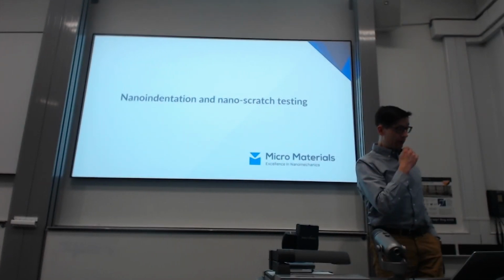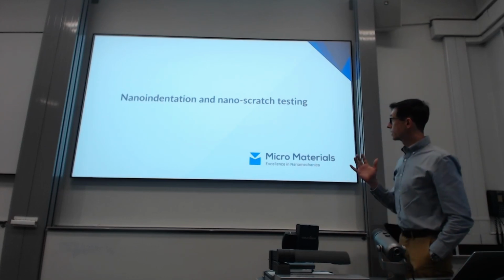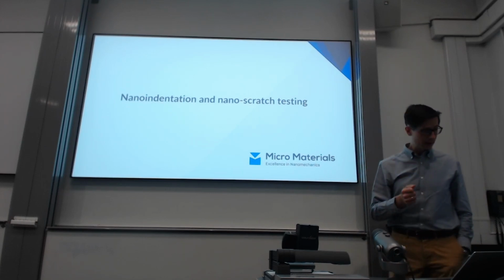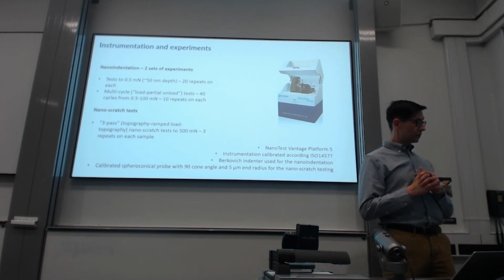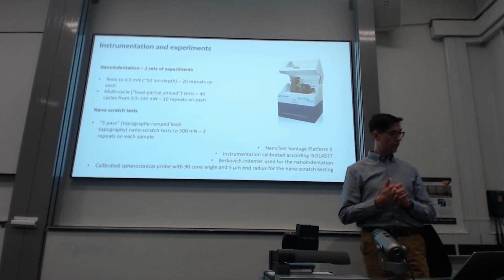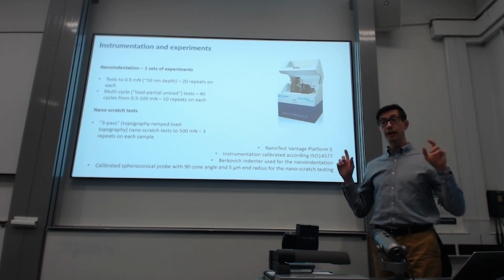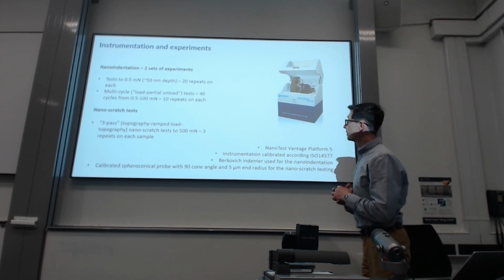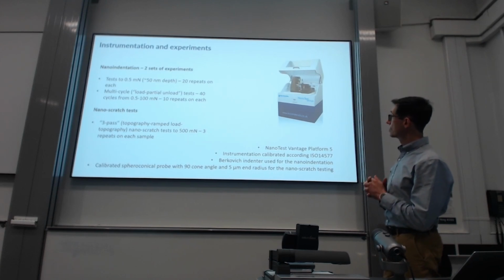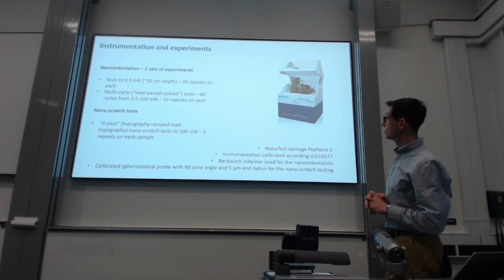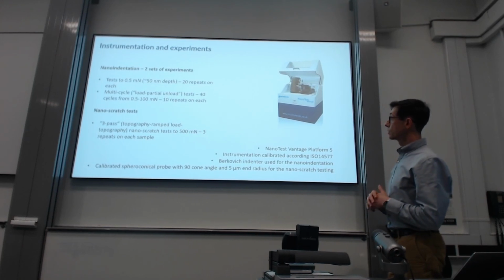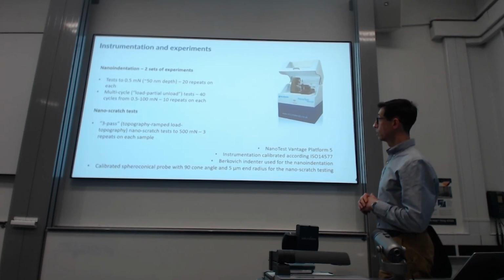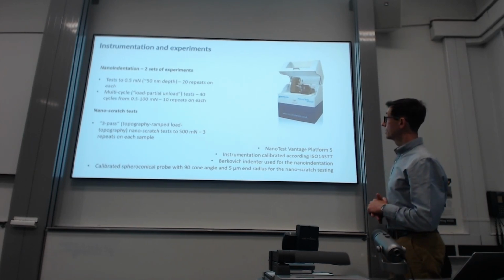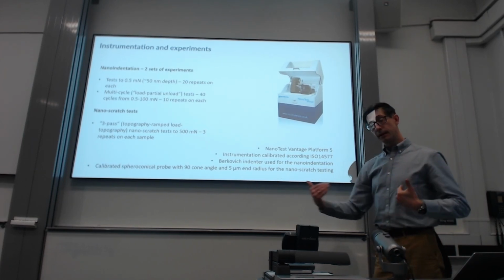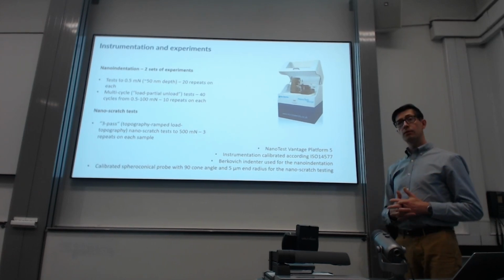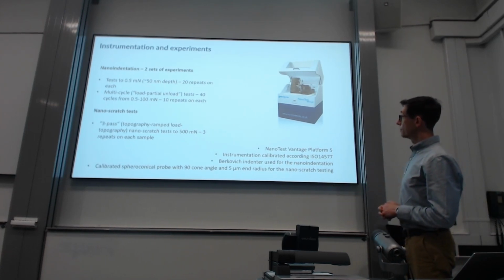So moving on to mechanical characterization, and starting with nano indentation and nano scratch testing. For nano indentation, we ran two sets of experiments. We started with, let's call it classical nano indentation, so 0.5 millinewtons, 20 repeats on each indent to 50 nanometers depth. And then we also ran multi-cycle, so-called load partial unload nano indentation, very helpful in terms of understanding the hardness and elastic modulus distribution in terms of depth.